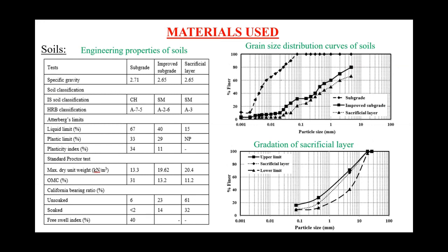Black cotton soil is used for the construction of subgrade, which has a low soaked CBR value, which forms a weak subgrade. And IRC SP 72 recommends a 100 mm improved subgrade over the weak subgrade. For that, we have used another soil, for which the criterion is that the soil should have a soaked CBR value greater than 10%. We have used a soil which has a soaked CBR value of 14%.